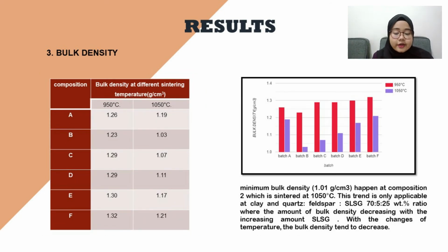I'll continue with the result of bulk density. The minimum bulk density, which is 1.01 gram per centimeter cube, happened at composition 2, which is batch B, sintered at 1050 degrees Celsius. This trend is only applicable to clay and feldspar SLSG at ratios of 70, 5 and 25 weight %, where the bulk density decreases with the increasing amount of SLSG. With the change of temperature, the bulk density tends to decrease.